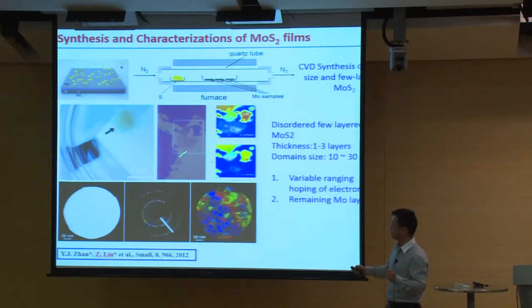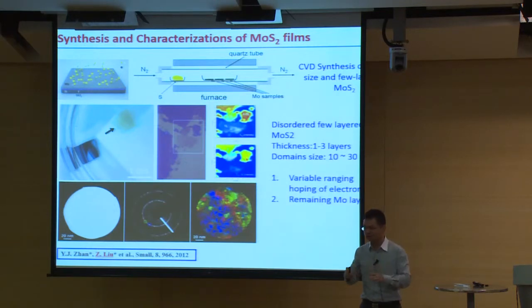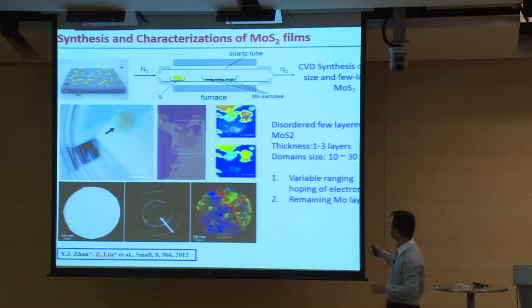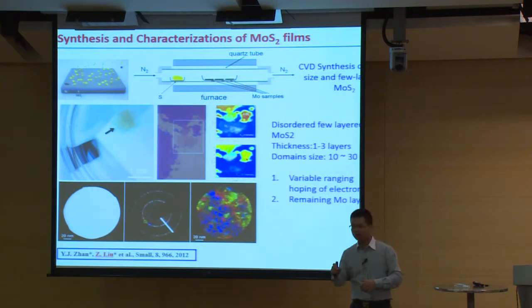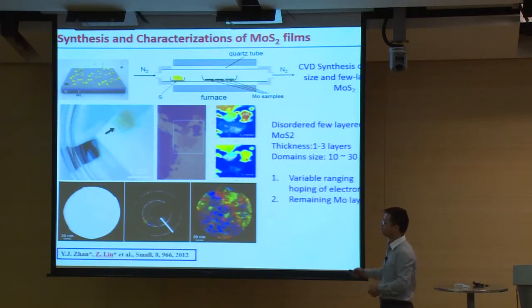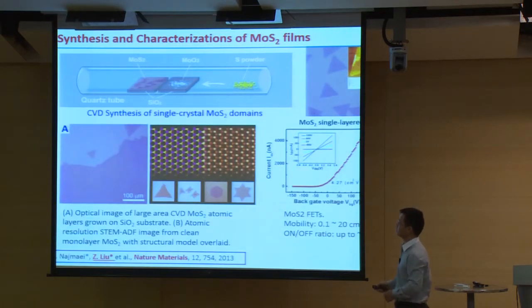And using the Raman mapping, using the bright field image to the false color dark field image, we know this film actually consists of a lot of nanoscale flakes. The size of these flakes is tens of nanometers, and thickness from 1 to 3 layers. But this is not enough, because if we want to use this material to make FET devices, the electron will hop from 1 flake to another flake. So the performance will be pretty low. And also, if this thin layer of moly hasn't reacted with the sulfur completely, the remaining moly layer will destroy this device. So to improve the quality of these materials, we replace the moly films with the moly oxide.